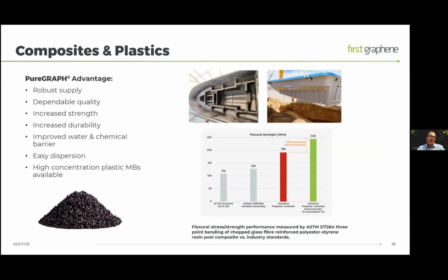Some recent work that we just published an update on from the University of Warwick in the UK shows that the PureGraph materials are readily incorporated into thermoplastic matrices through normal extrusion processes. We can make very high concentrations, so 30% by weight concentration master batches, and plastic master batches are now available from First Graphene. So if you have an interest in plastic master batches with graphene, please contact us.